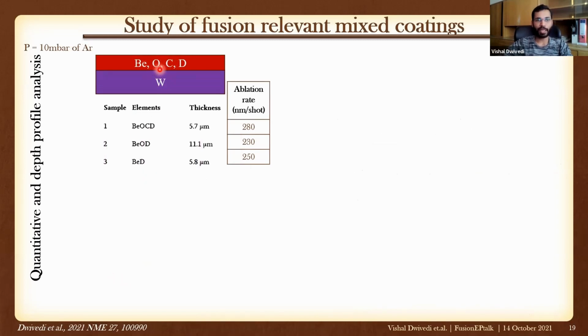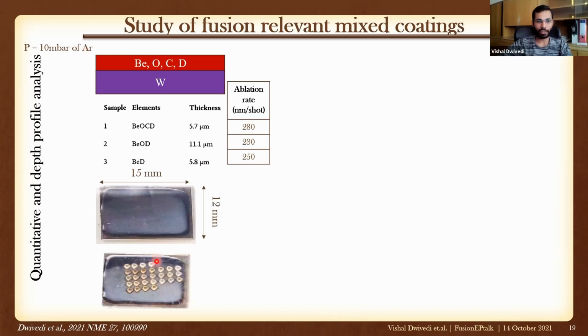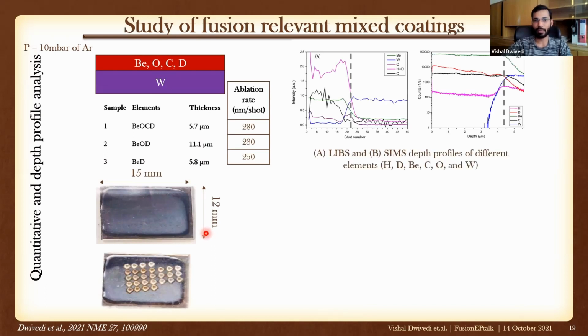After that, we studied beryllium, oxygen, carbon, deuterium related coatings. We had the possibility to study 3 different samples of 3 different thicknesses. We have also calculated the ablation rate. This was measured under 10 millibar of argon pressure. This is the real sample, so you can see the ablated one and one without ablation. This is the dimension of the sample, 15 mm and 12 mm.